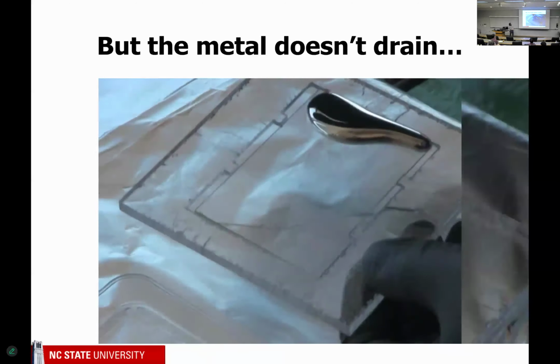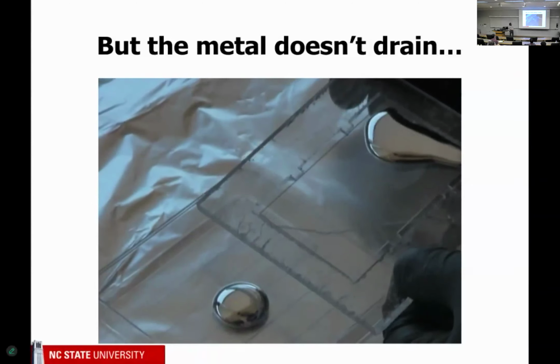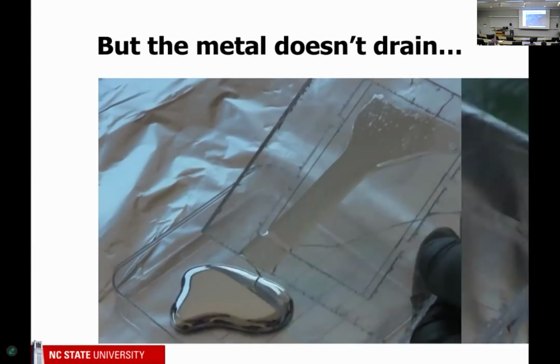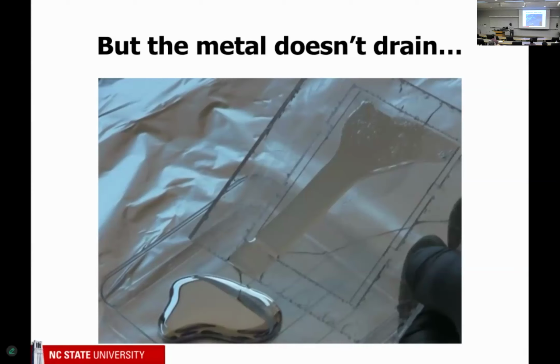So here you take a puddle of liquid metal, and sorry for the video acting funky, but if you tilt it, you'll see that the liquid flows down the glass slide just as you would expect if you took a puddle of water and you tilted it. It would just flow down. But unlike water, the weird thing, and we don't understand this, is it forms a film. And this film is stable. That's weird because this has got a viscosity like water. It's got a surface tension that's enormous. It should not make a film. Now, obviously, the oxide's playing a role here, but what it's doing exactly, we don't know.